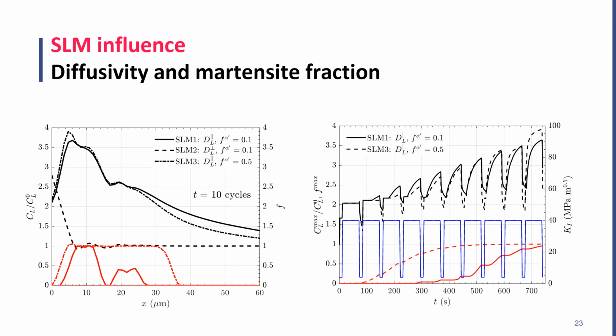Considering this presented numerical framework, we simulate hydrogen redistribution during dwell fatigue. We can see here, on the right, the maximum hydrogen concentration in lattice sites normalized by the equilibrium concentration. This is plotted with the black lines, and we can see how the maximum increases because hydrogen diffuses to the fracture process zone. Comparing a martensite fraction of 0.1 with 0.5, we can see that at the beginning, a higher martensite fraction, the dotted line, results in a lower concentration because diffusivity is lower in comparison to a material with a higher content of beta phase. However, when hydrate starts to form, the formation is faster for a high martensite fraction, as expected, and so the hydrogen concentration increases faster.